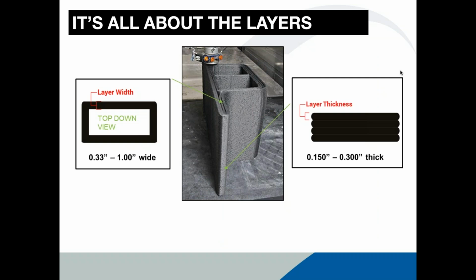So with large scale additive, it's really all about the layers. And you know, as I said before, 3D printing is putting a layer of material down, and then on top of that, and on top of that, and so forth, till you build up your part. So the reason why we print so fast is really the size of our layers. So if you look on the left-hand side, the top-down view, we can print anywhere from 0.33 of an inch to a full inch wide of a plastic layer. And then on the right-hand side, the layer thickness, as you're building up, that can be anywhere from 0.15 of an inch to 300 thousandths of an inch. So we're printing very thick and very wide beads of plastic, and that's how you get that kind of corduroy effect that you see on the part there. So the parts come off the printer fairly rough.